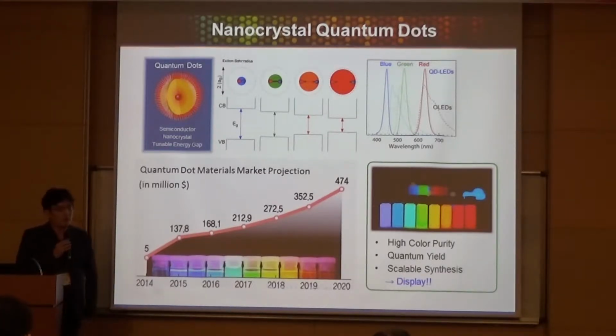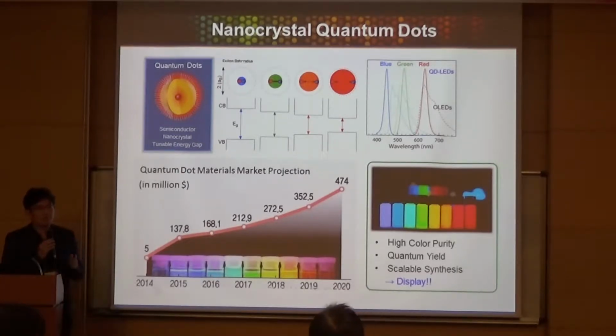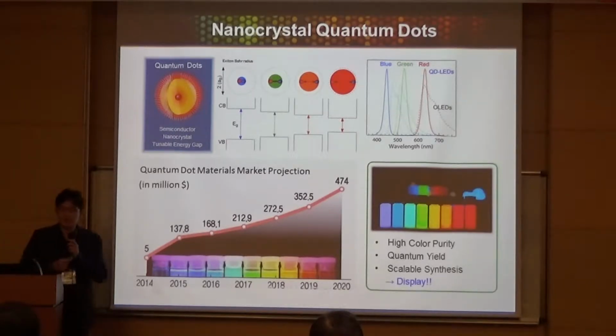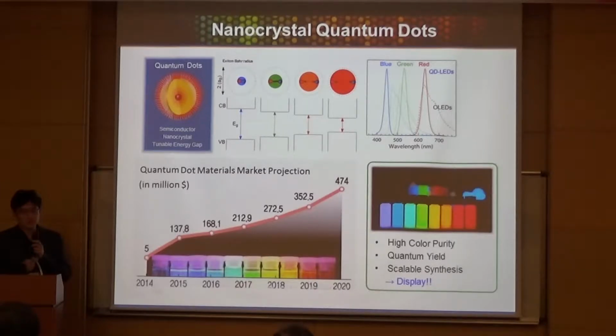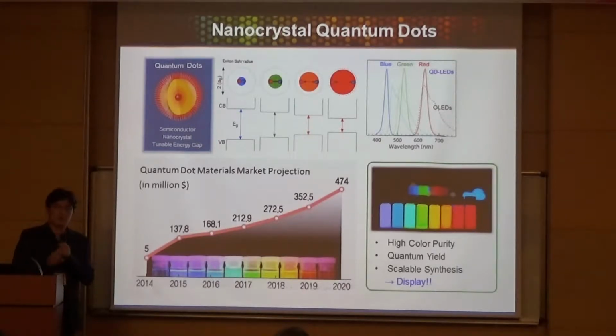Those who are familiar with quantum dots can just bear with me for one or two slides, but for those who are not truly familiar with this material, these are semiconductor nanocrystals that show the quantum confinement effect when the size of the material is smaller than the typical separation between electron and hole in bulk space. Then when the size becomes really small, the electron and hole wave function fills this boundary, and because of this confinement, the energy gap is going to change. And it's going to change as a function of the size, and you can tune this energy gap using the size of a material. With one set of composition, one set of material, you can make materials that emit light in different colors, different wavelengths.